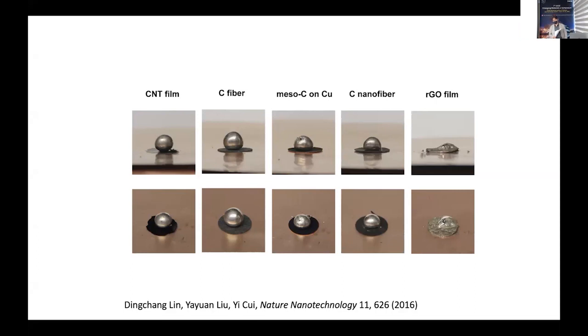Apparently, there is a wetting phenomenon right here, similar to water's wetting, hydrophobic and hydrophilic. For the lithium case, we call the new terms lithophilic and lithophobic. Lithophilic describes a wetting phenomenon of molten lithium. And the reason graphene oxide allows lithium metal to wet is because it has all these polar functional groups. And lithium reacts with the OH functional group, for example, and the delta G of the reaction is negative. So it's actually a wetting surface.